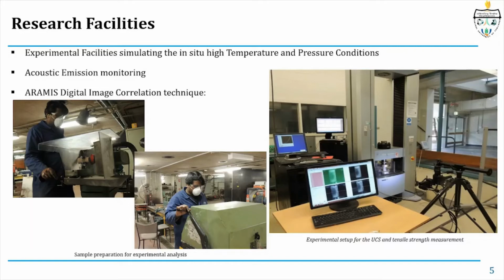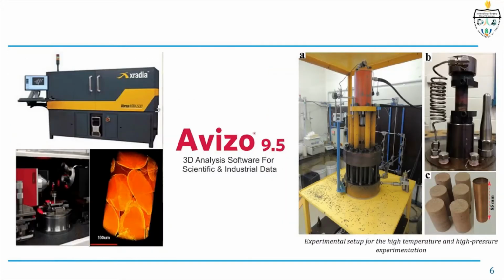The acoustic characteristics of the mechanical deformations of the rock were captured using AE sensors attached to the specimens. The development of strains in the samples was captured by Aramis digital image correlation technique and strain gauges. Aiming for the in-situ rock mechanical behavior, I have performed experiments using the high pressure and temperature triaxial ring present at the 3GD laboratory, which can go up to a maximum temperature of 300 degrees centigrade and a pressure of 140 MPa. After the mechanical test, the failed samples were used to investigate the shear boundary characteristics at different temperatures and pressures using the Australian synchrotron facility present in Melbourne.